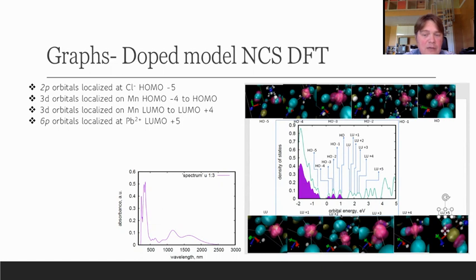But the ionic radius of manganese is smaller than the ionic radius of lead, and substitution doping reduces pressure on the walls inside this chamber. So in order to reach equilibrium, one needs to compress, make the cell smaller, and re-optimize the geometry once again. And this operation had not been done at the time when Salim generated these figures and data. If this operation is done correctly, the energies become much closer to realistic values. I think the next slide that Salim is going to show will demonstrate the data done after this optimization of cell size is complete.